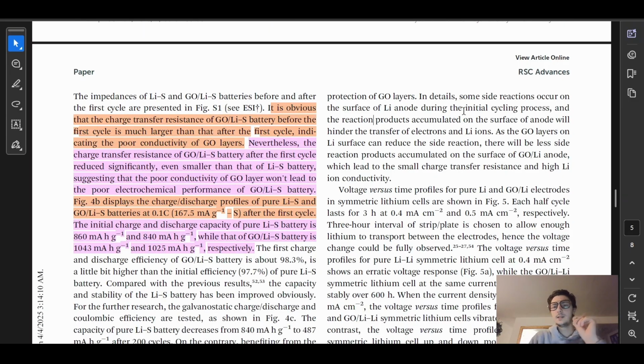Interesting. In detail, some side reactions occur on the surface of the lithium anode during the initial cycling process, and the reaction products accumulated on the surface of the anode will hinder the transfer of the electrons and lithium ions. As the graphene oxide layers on the lithium surface can reduce the side reactions, there will be less side reaction products accumulated on the surface of the GO lithium anode, which leads to the small charge transfer resistance and high lithium ion conductivity. Cool. This also is an interesting sentence. I'm going to highlight this one in orange.